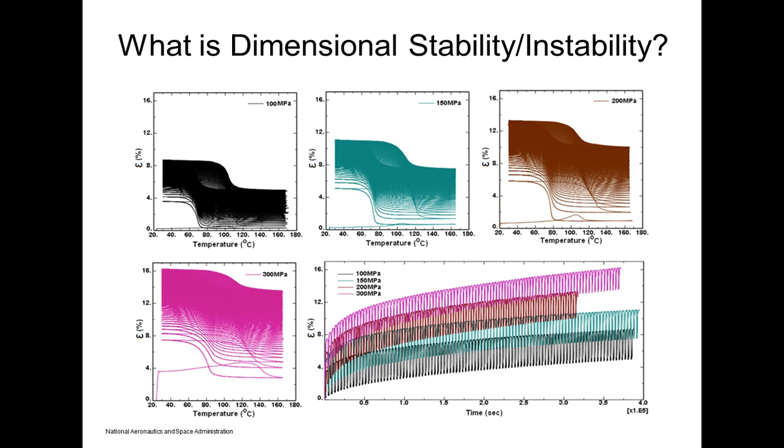And as you can see, the actuation characteristic that we talked about before is slowly evolving in the deformation field. So we're going from some level of strain around 4% or slightly above it, and then it's eventually evolving with time and reaching a saturated state somewhere on the order of 8 to 12 to 14 to 18%, depending on the external stress that was applied to the system in this particular case. And of course, until that level of walking from cycle to cycle, or level of open loop strain as we call it in the community, reduces to a certain level, the reproducibility of the actuation stroke is not good enough to use in an intended application.